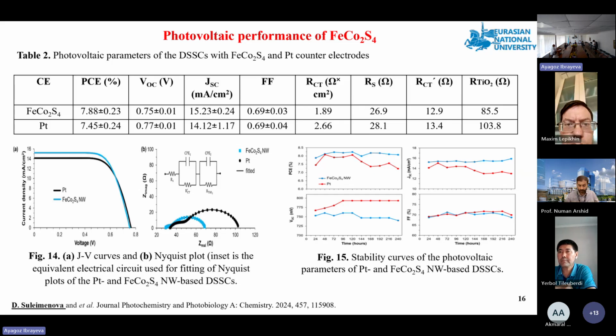This plot shows that the charge transfer resistance at the counter-electrode electrolyte interface is much lower than that of platinum, enabling faster electron transfer, a higher iodide concentration, and accelerated dye regeneration, which explains the higher JSC. Over 3 days, ferrum cobalt 2 S4 devices maintain stable PCE, JSC, and FF, while platinum cells declined. VOC decreased slightly for ferrum cobalt 2 S4 due to increased recombination at the titanium dioxide dye electrolyte interface, but overall the cells remain highly stable and efficient.